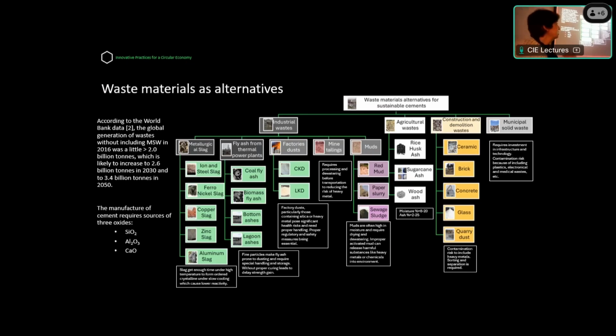Another group are dust from different factories like cement kiln dust, lime kiln dust, and ferrosilicon. Microsilica, which is a byproduct of ferrosilicon factories, but this dust again should be densified due to handling and storage, not to cause problems for safety, for health, and also for using this material. Again, the variation of different batches can be high, and it possibly contains some hazardous material, so we should be careful about the safety of using this material.